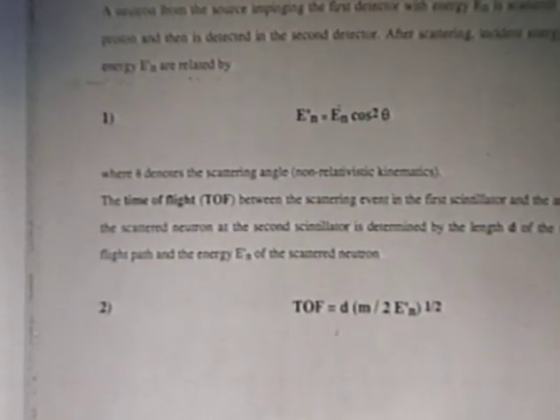There is a problem anyway. We need to have the first detector of a small size, otherwise we will have multiple scattering. And on the other side, to have enough sensitivity, we need for the second detector a large angle to collect most of the neutrons which are scattered. And this poses another problem, which is that we have a larger range of angles, and so a larger uncertainty about the energy, because from the time of flight we need to measure the energy of the neutron which was impinging on the first detector.